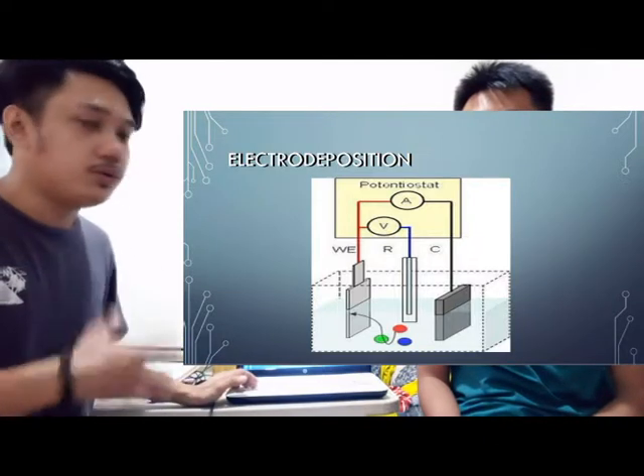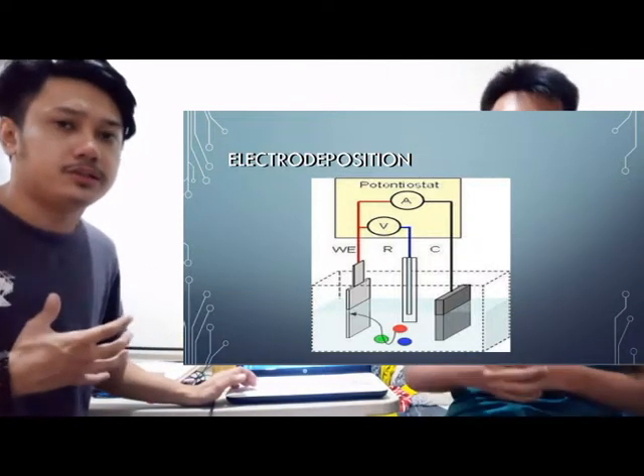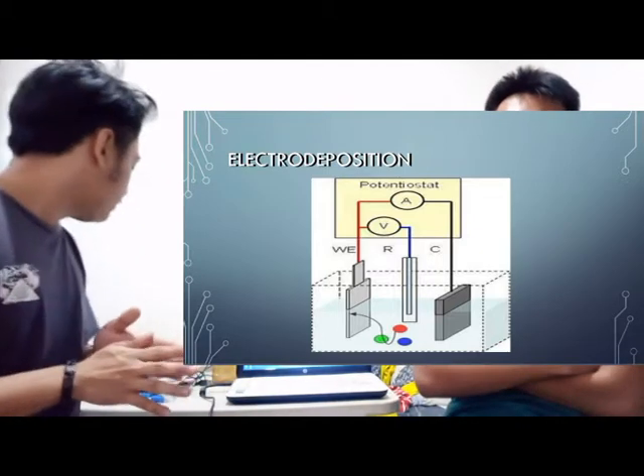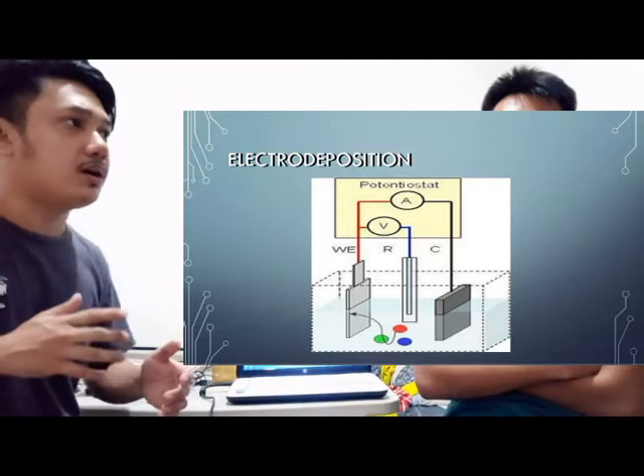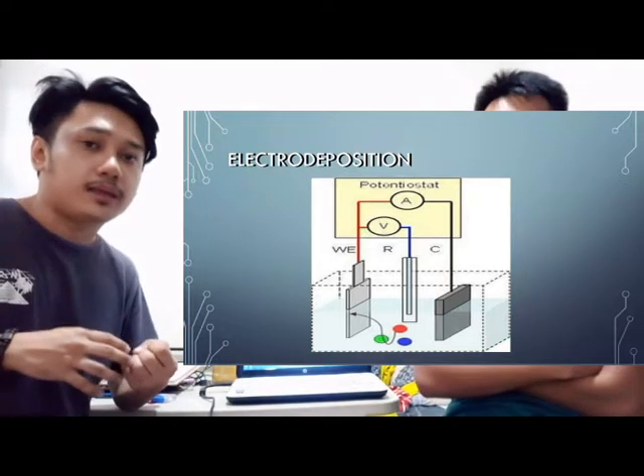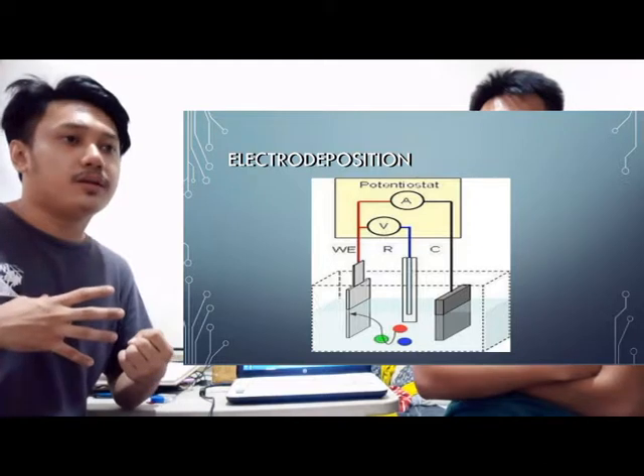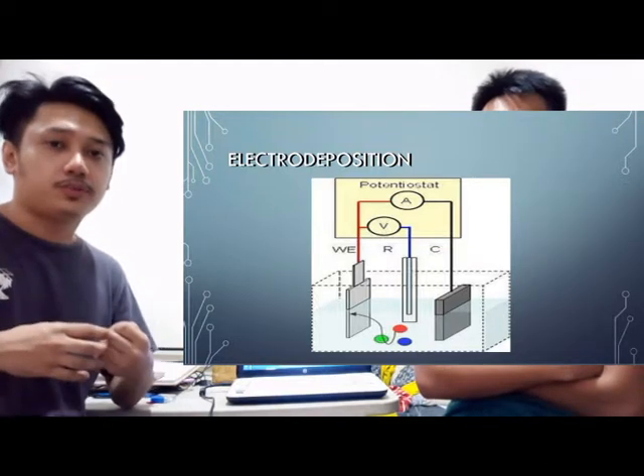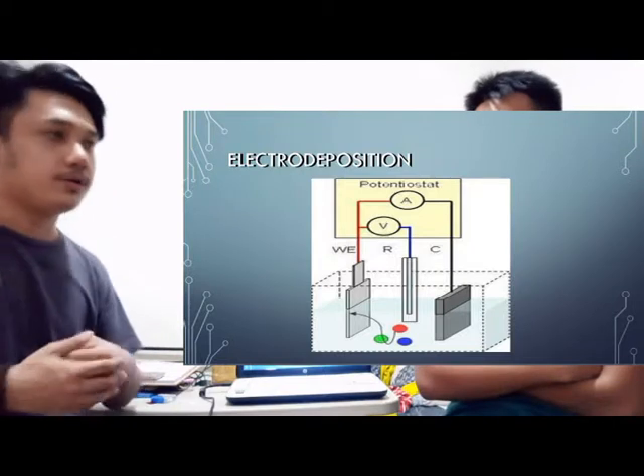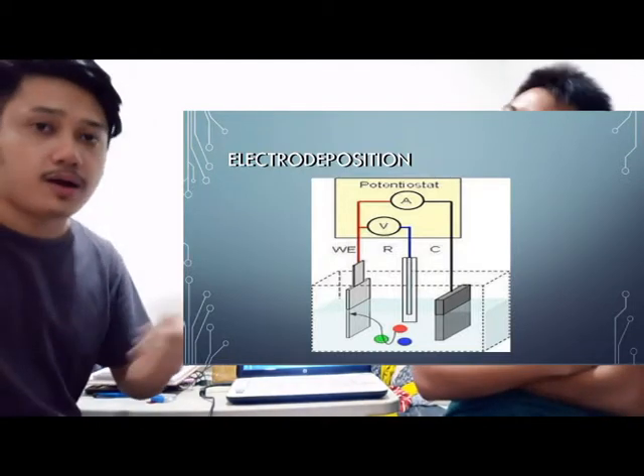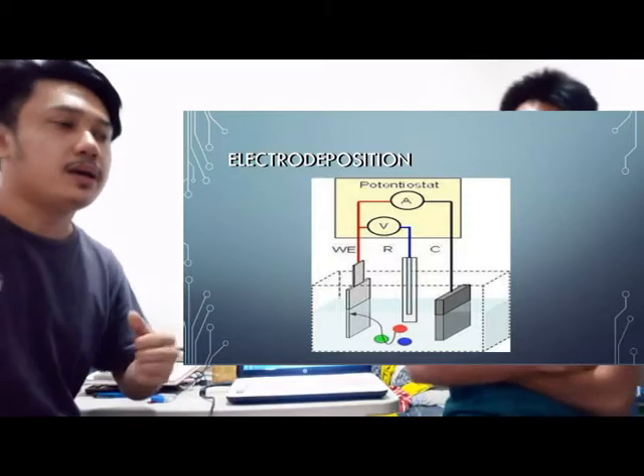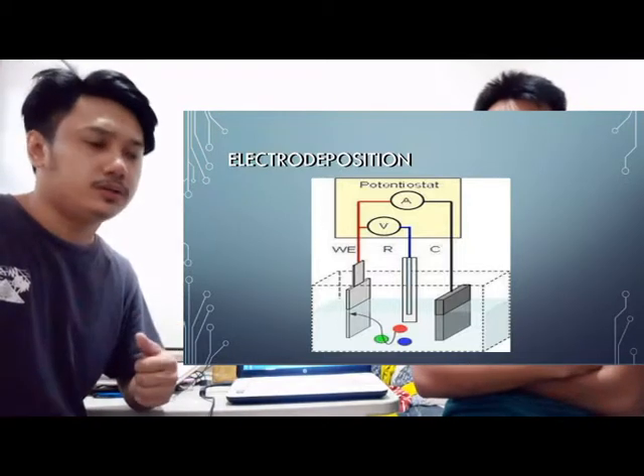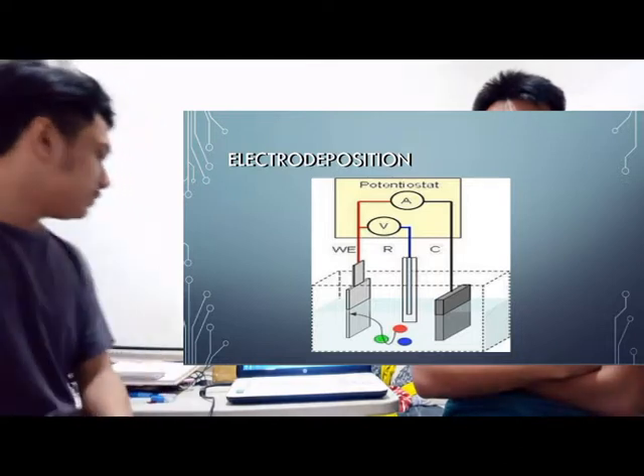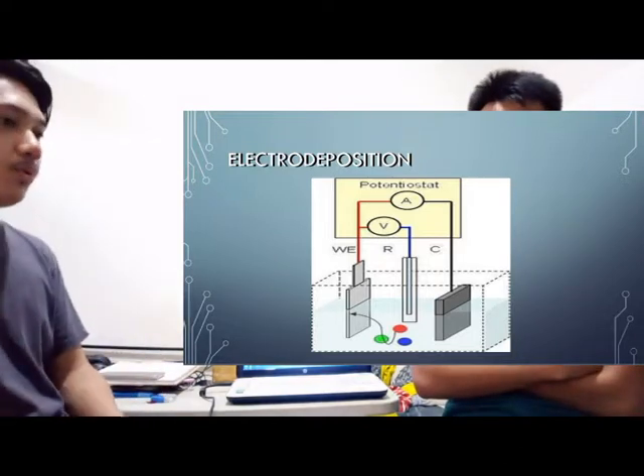So we chose to go the electrochemical route due to several reasons. First of all, as opposed to chemical synthesis, this method does not require a catalyst, which means that the electrodeposited polymers are essentially pure and homogeneous. Another thing is that it allows us to have a finer control over the thickness of our coating, and it also allows us to achieve crystallinity easier. So my partner here will discuss how polyaniline was used as an anti-corrosion coating in the past.